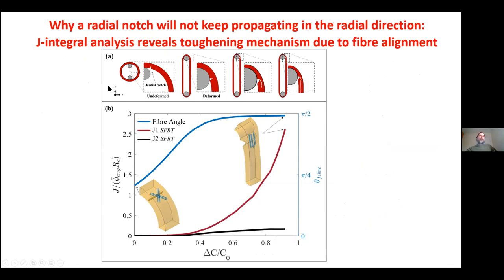So we checked out the hypothesis using some cohesive zone modeling. Basically, we cut a notch here and we stretch, and according to our hypothesis, the crack should not follow the notch, but it should kink and grow between the layers. The reason we think that is because our simulation says that in an artery, all these collagen fibers are in the plane, in the circumferential direction, in the circumferential-axial plane.